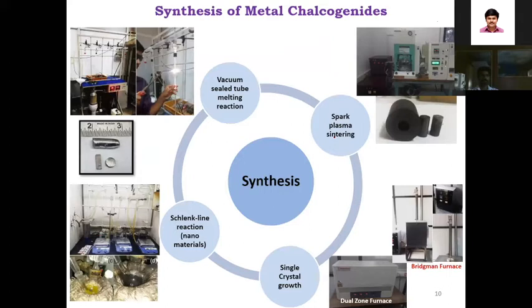We can synthesize heavy metal based selenides, tellurides, and sulfides in the form of bulk material by vacuum sealed tube reaction, or we have spark plasma sintering to give high dense samples. We can grow single crystals by Bridgman furnace as well as dual zone furnace. Also, we can make nanoparticles by solution reaction, by tuning the chemistry of the reaction. So we have the capability to grow different kinds of samples in this field, from bulk to nano to high dense to single crystal.